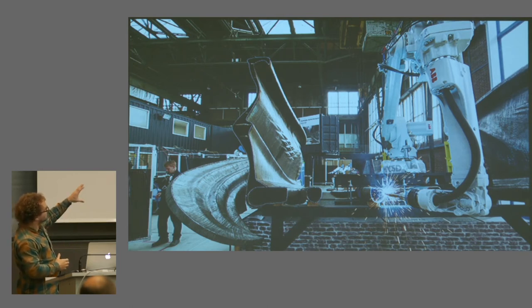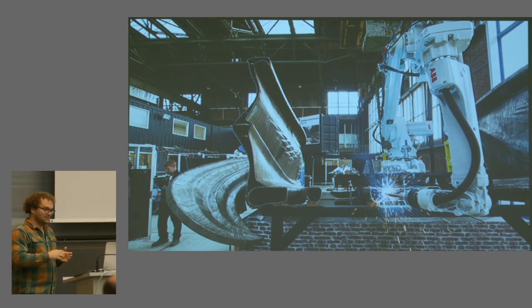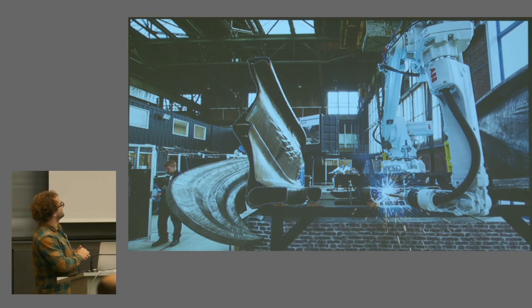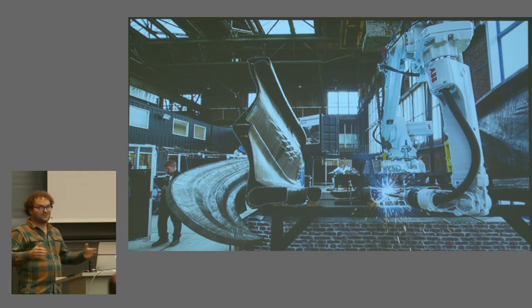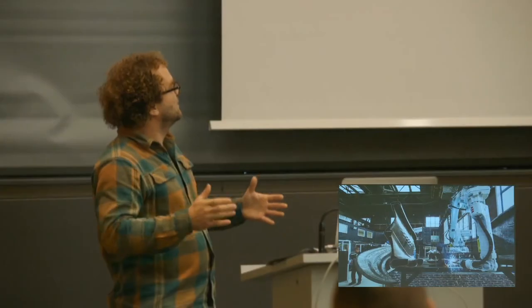And yeah, we also put the robot on top, not yet with a mobile support, but we printed horizontally, which worked, but it was almost half a kilo per hour, and we rather had around 2 kilos per hour as we had to deposit 6,000 kilos. So yeah, the gain from increasing the speed slightly was clear. So we chose, as the object is to print a 3D bridge, let's print it in very big parts and then assemble it together.